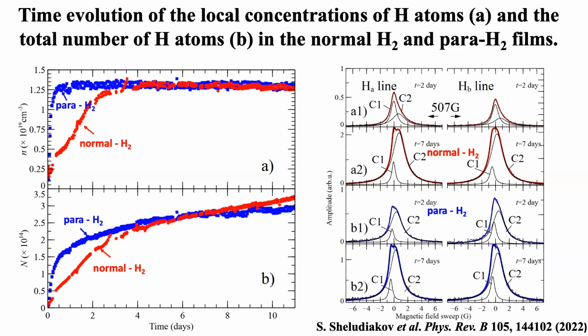As I mentioned before, there's fast accumulation at the beginning in para-hydrogen, and after that, the local concentration is saturated. The total number in para-hydrogen is initially higher, but after 6 days it became equal, and after that it became smaller. This is again the same analysis of the kinetics of the changes of the spectra.